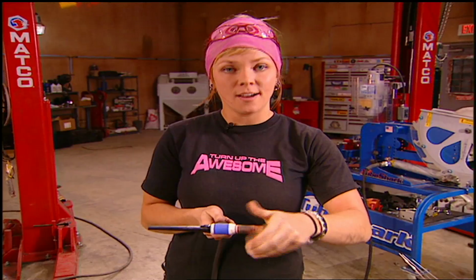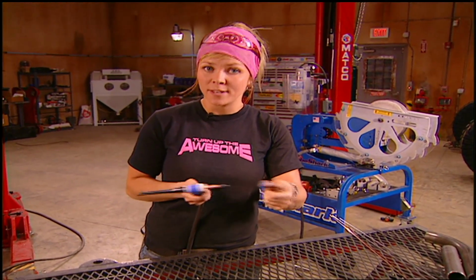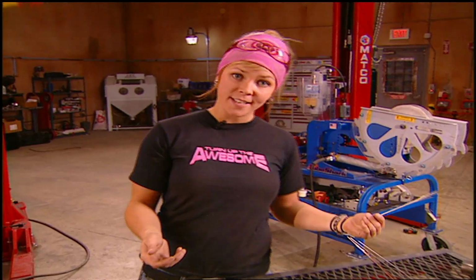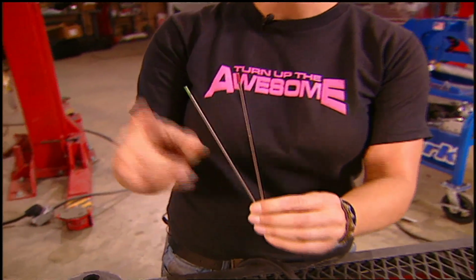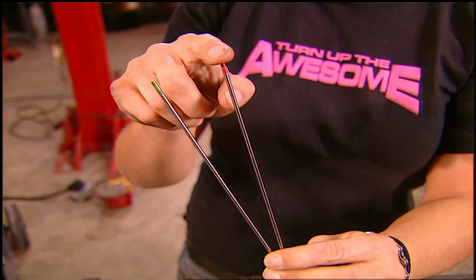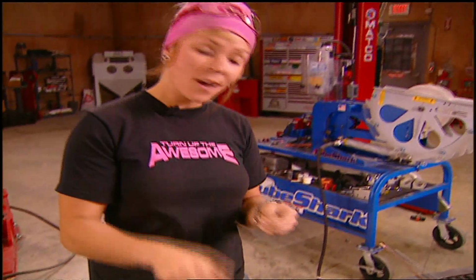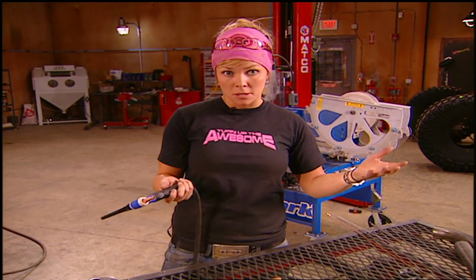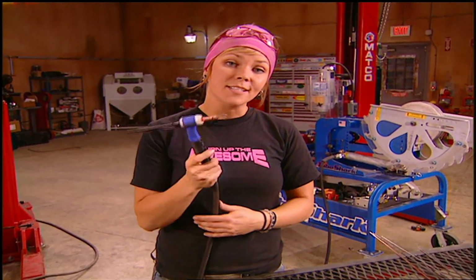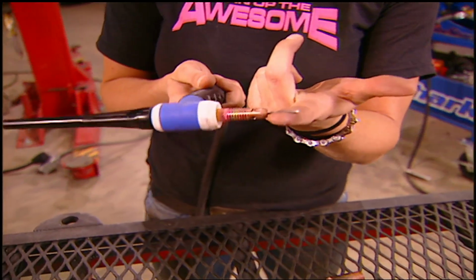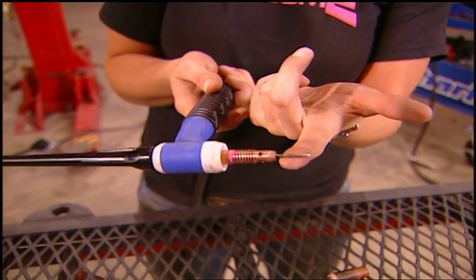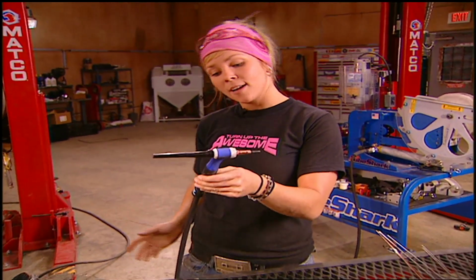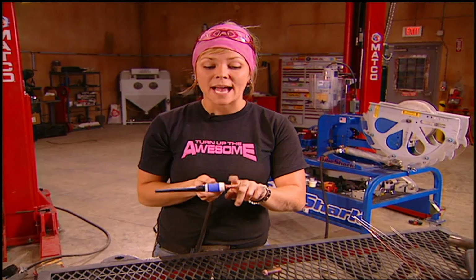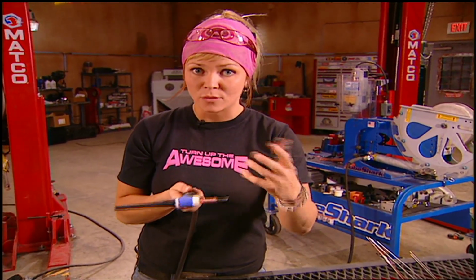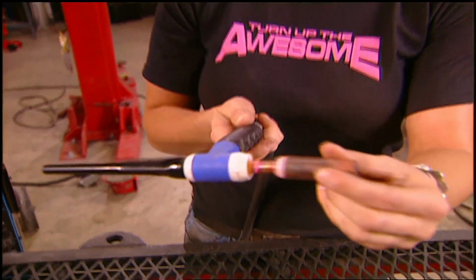Inside of this torch is the tungsten, which is where tungsten inert gas welding gets its name. Now, tungsten comes in different sizes depending upon the thickness of metal you're going to be welding. You have 100% tungsten for aluminum, and you have 2% thoriated, which is an alloy in the tungsten, for metals like stainless steel, chromoly, cast iron. Now, this electrode is what delivers the arc to create the molten puddle for the weld. And because it's made of tungsten, it's not going to melt itself. So the gas is going to come up through the line, through the torch, and through this gas lens, which is going to eliminate the turbulence for the gas cloud, which is then focused by the cup for the weld.